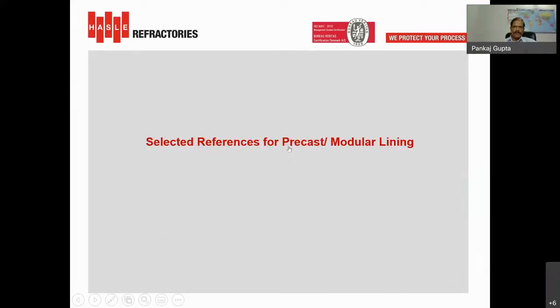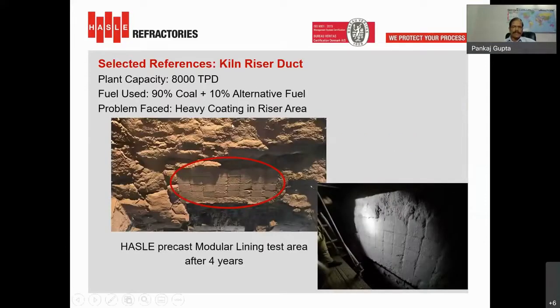Now coming to the selected references, this is a case for an 8000 TPD plant using 10% alternative fuels. This plant was facing heavy coating in the riser area. You can see the coating pattern on the castable surface, while there is no coating formation on the surface of the modular lining. The plant was able to achieve 4 years life with this lining. This picture is after 4 years.